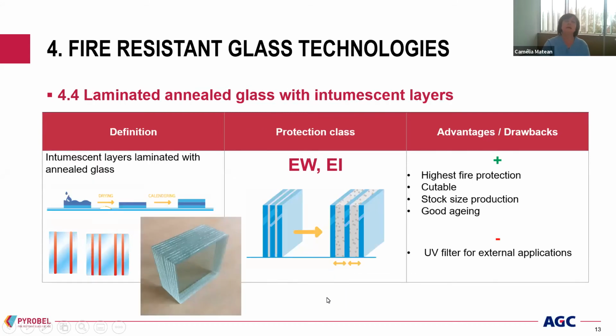And then we pass to the most protective glasses, EI class. In this category, we have laminated annealed glass with intumescent interlayers. How is this glass produced? The intumescent liquid layer is poured on a sheet of glass. Then it's dried in order to obtain a hard and transparent interlayer. And then all these glass plus layer are stacked on top of each other in order to obtain multi-layered glass with 2, 4, up to 10 layers in a glass according to the rating we can reach.